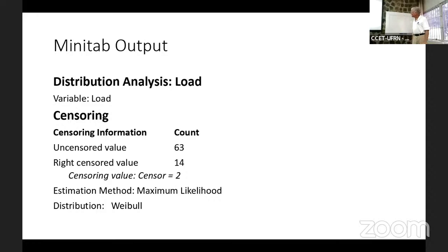There were 77 items that we did in the tensile test, and it's unusual, but we actually had right-censored observations. The original test at Lawrence Livermore Lab from 1995 to 2005 had metal clamps for carbon fiber. What does metal do with fiber? Cuts it. And if you cut part of the outer layer of a cord, are you increasing or decreasing its strength? It's a bad thing.